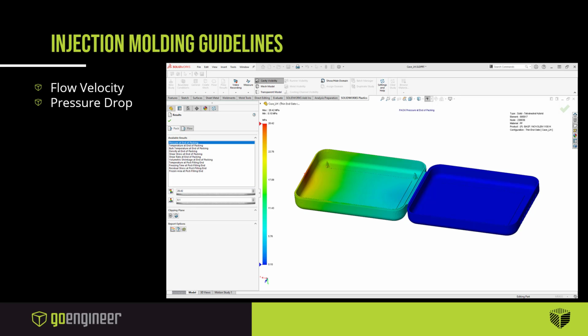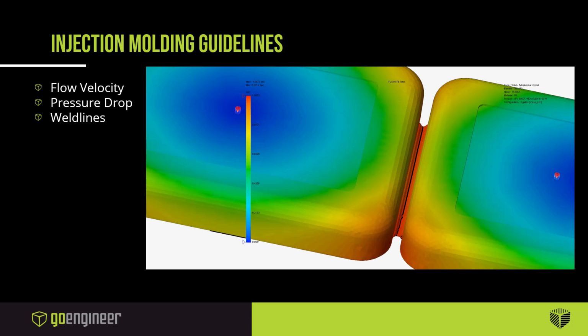One thing that we can also do is change our gate positioning or actually add multiple gates to help with the pressure drop. But if we add multiple gates, we need to keep in mind that we're creating two flow fronts. You have two material flow fronts that come together, and you're going to have a weld line between them. So this weld line is actually going to cause some issues in the part.